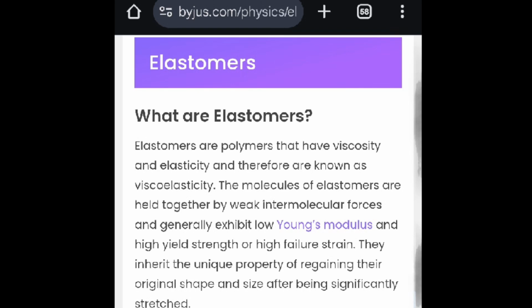The elongation of modified bitumen does not even meet 100%, meaning that modified bitumen cannot stretch 2 times its size, period. It's not about whether or not it retains its original shape. It doesn't even reach that criteria. It can't stretch enough to even test if it's elastomeric.